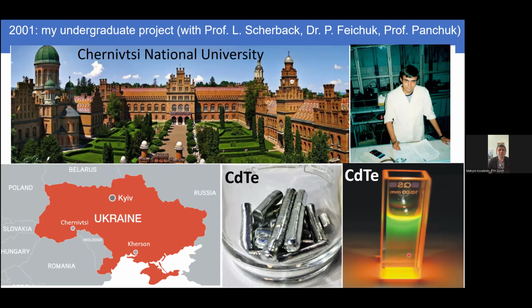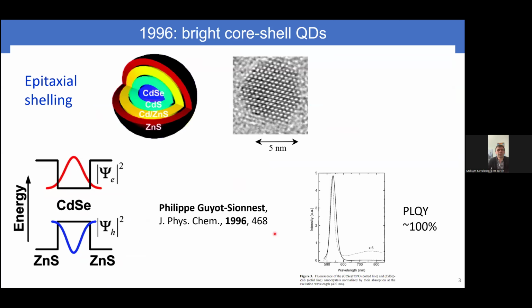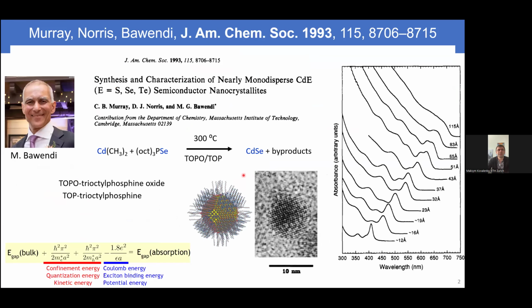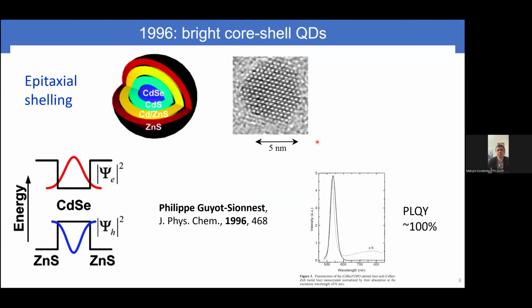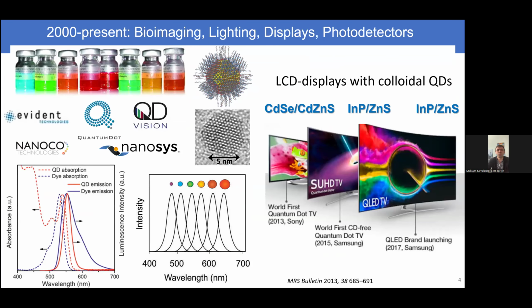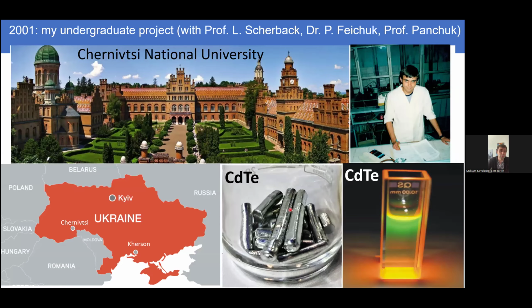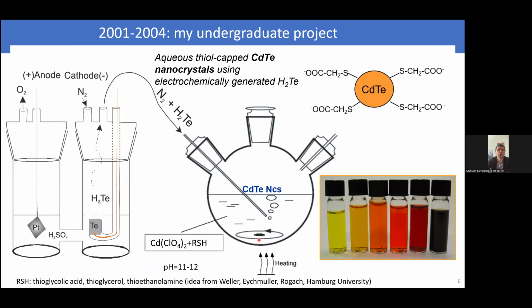But of course, back then we could not afford these sort of organometallic, air-sensitive reagents and things like that. So we worked with much simpler chemistry, and that turned out to be equally or comparably good. We had a lot of tellurium. So from tellurium you can produce hydrogen telluride. Hydrogen telluride you bubble through water, which contains cadmium reagents, and with a bit of heating you easily produce cadmium telluride quantum dots.